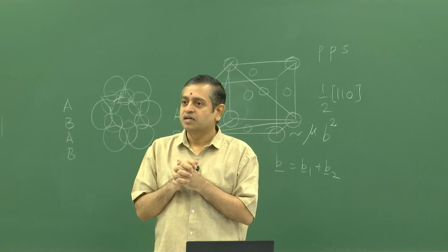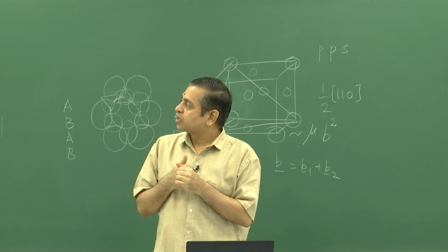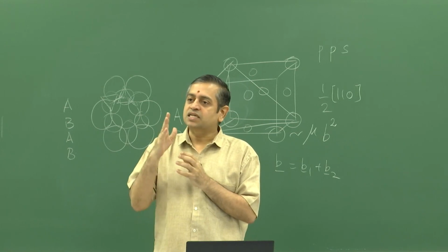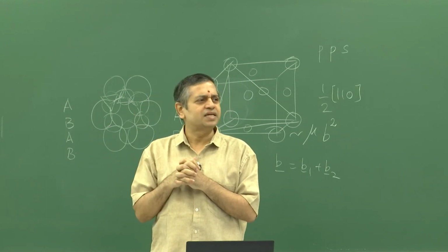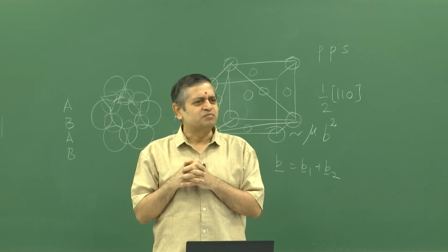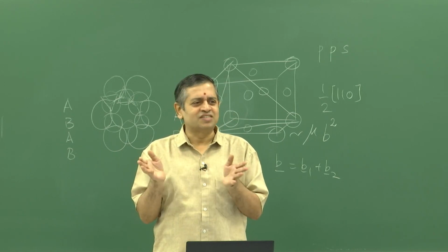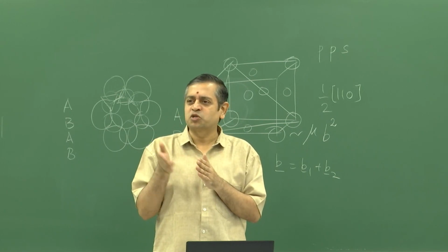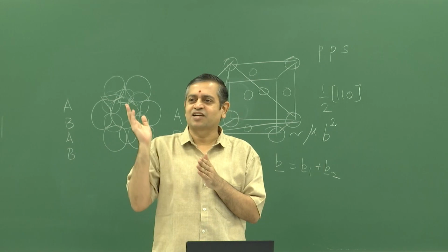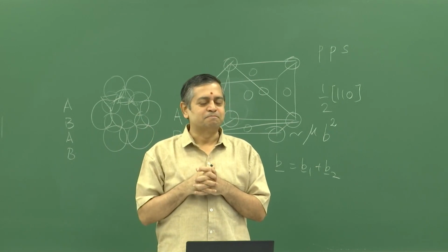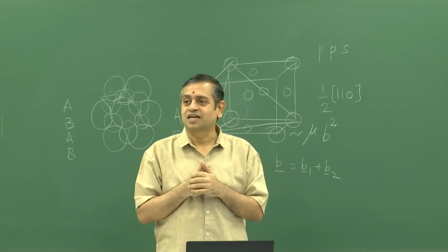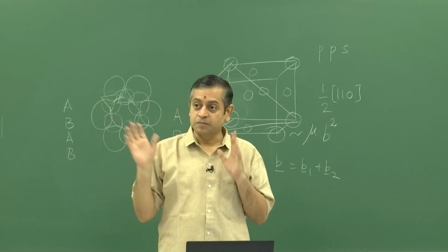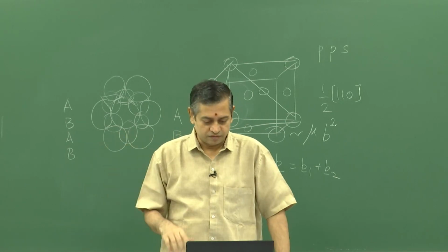No, 40 millijoules per meter squared is at room temperature. As the temperature goes up, they also tend to, I think, increase or some such strange thing. Because these are free energies, I always thought that they will decrease, but experimentally as well as in several simulations, it is reported that with increasing temperature, these stacking fault energies increase, which is another strange thing. But yeah, it is at room temperature, and these simulations are also at room temperature, at 300 Kelvin we evaluate.